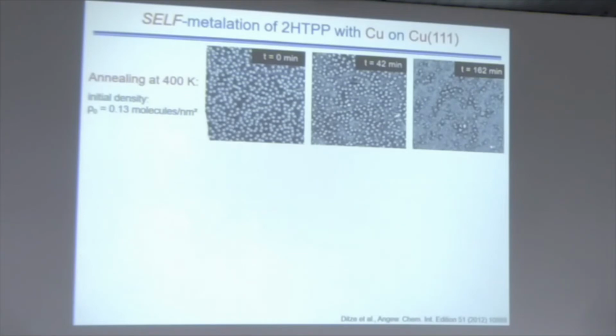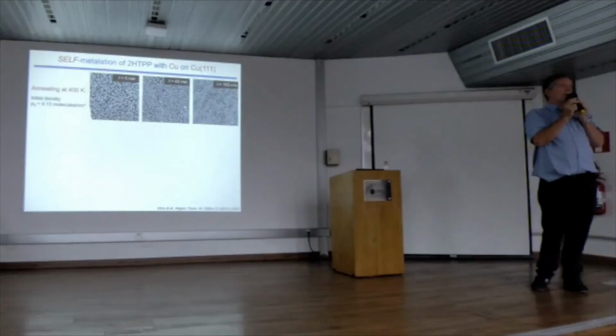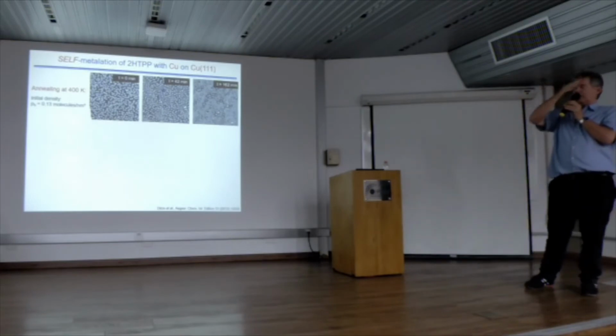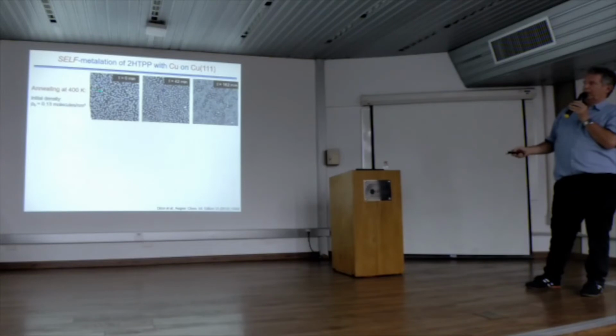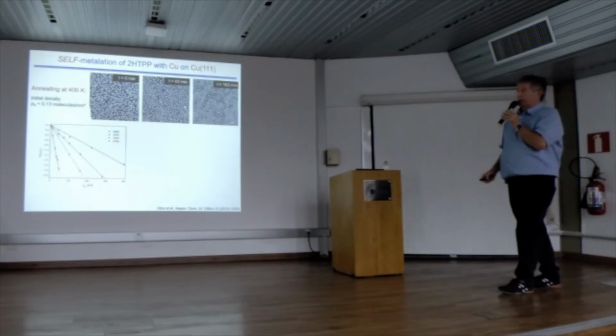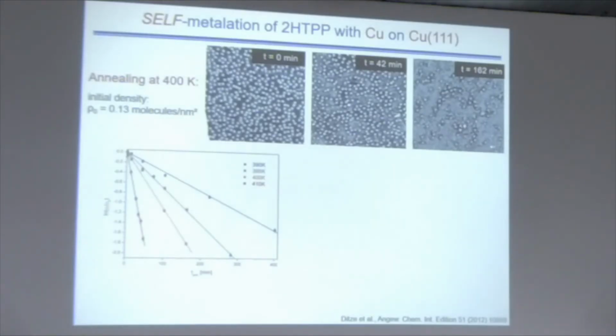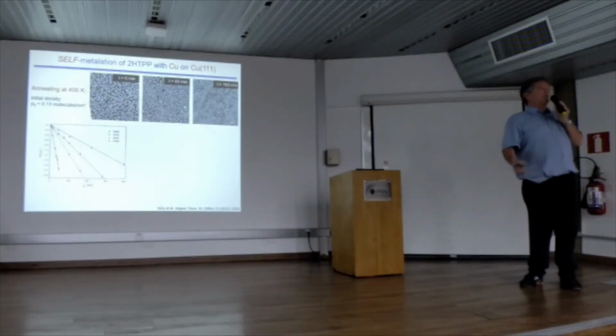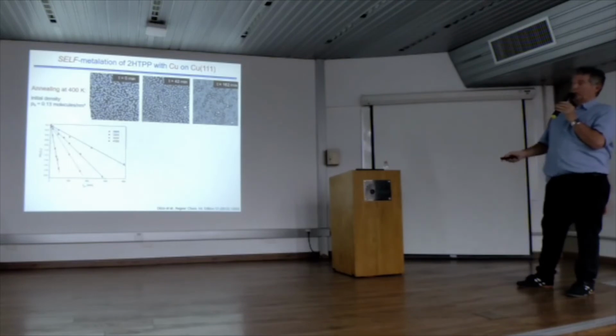And now you do a very simple chemical reaction analysis. You count, like in radioactive decay, the number of atoms that have not decayed yet. You have a starting signal, and then they decay, and then you have less and less. And this is the same here. You just count the number of bright protrusions. And then you plot the number of molecules, and if you're clever, you plot the logarithm of them as a function of time. If you plot the logarithm of a concentration as a function of time and you get a straight line, you have a first order reaction. Like radioactive decay, you have an exponential decay, and if you plot the logarithm of an exponential, you get linear behavior. And the slope gives us the rate constant.